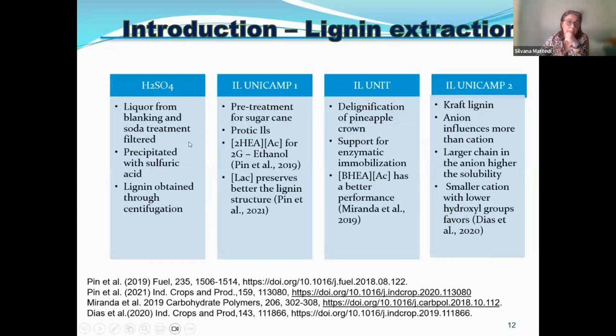We were not focused on lignin extraction for this specific work. We basically use the traditional method, bleaching and soda treatment. The liquor is filtered, precipitated with sulfuric acid, and you obtain lignin through centrifugation. But we did some work on lignin extraction before.